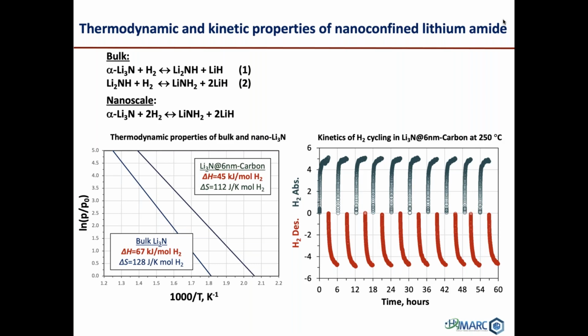Now, this slide gives you a little bit of a demonstration of how significant this nanoscaling effect can be. Lithium amide is an attractive hydrogen storage material, but its enthalpy of desorption, that is the heat required to desorb hydrogen, for the bulk material is about 67 kilojoules per mole, which you see in that plot in the lower left. If we infiltrate a porous carbon that has pores about 6 nanometers, we find that we can reduce that by over 20 kilojoules per mole to about 45. And that's a huge effect. That's enough to drop the temperature of onset of hydrogen release by several hundred degrees.